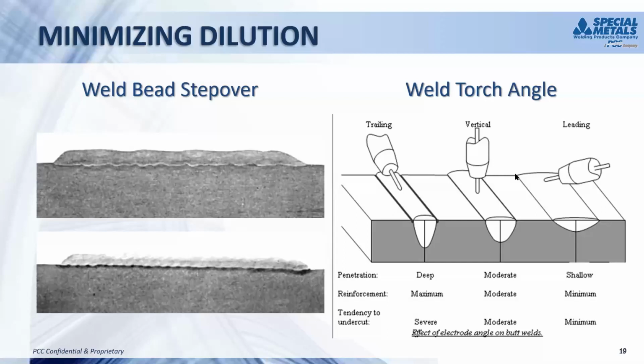What we've got on the left side is a very wide step over, something in the neighborhood of a 50% or less bead overlap on the top, and then the bottom is probably closer to about a 60 to 75% bead overlap. And as you can see, that bottom fusion line becomes straighter, which gives you less potential problems. You're actually burning less of the base metal, so you've got less dilution. You're not pulling up as much of that iron, which can cause some problems and reduce your corrosion rates.